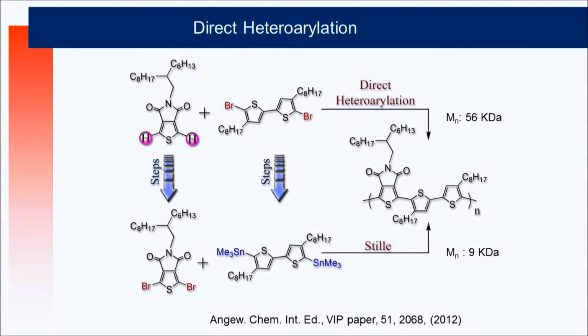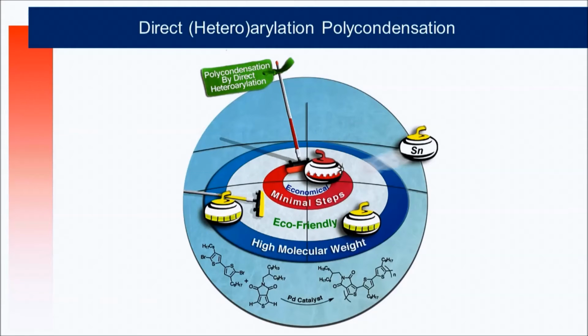It made a good splash in the field because it simplifies the chemistry completely. And that's how we transferred this message. It was published in Angewandte, so they're looking for TOCs which are spherical. So we tried with ice hockey, we made it. So we used curling. So instead of the Stille coupling, you get, in some cases, higher molecular weight. It's certainly eco-friendly. You get rid of any tin derivatives. You reduce the number of steps. Clearly, you reduce the cost of your materials for comparable applications. So it's very, very important in the field.